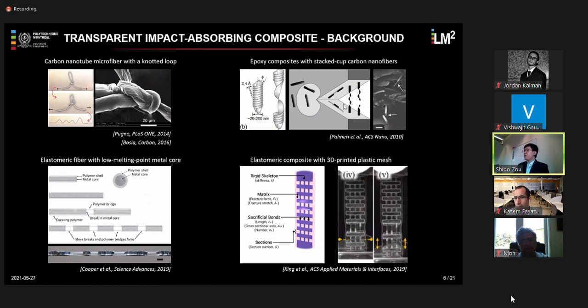And in the second example here, the researcher tried to introduce the stacked carbon nanofiber into epoxy composite. If you stretch a single stacked carbon nanofiber, because there exists a weak bonding in between the helical layers, when you stretch it, the interlayer bonding will be sacrificed, will be broken first, and they will release this hidden length along this fiber. And the researcher also added this kind of carbon nanofibers into epoxy materials to make this composite, and they also achieved improvements in terms of toughness.